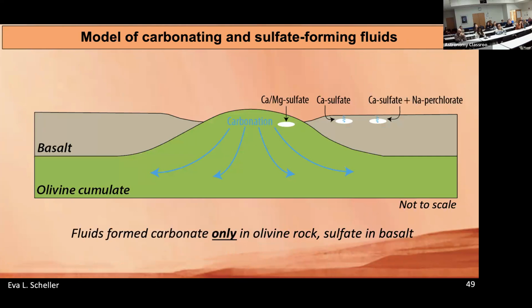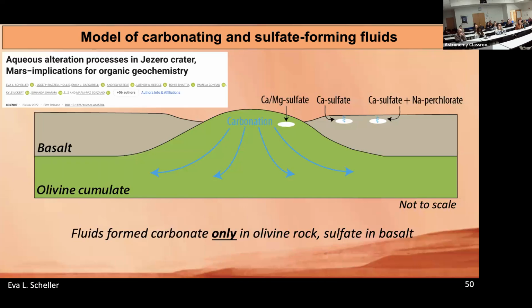So let's summarize these environments from the crater floor specifically. We observed this olivine cumulate with carbonation in it. There was some sulfate as well. When we look at the basalt, it doesn't have any carbonate, but it does sometimes have these sulfates that we observed. And so these are just the first results from the Raman spectrometer that is summarized in this little science report here, with a very big team behind this instrument, just showing what were the very first things that we observed on the surface of Mars, including all this stuff we just looked at.